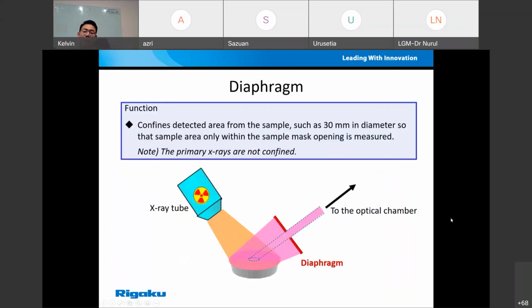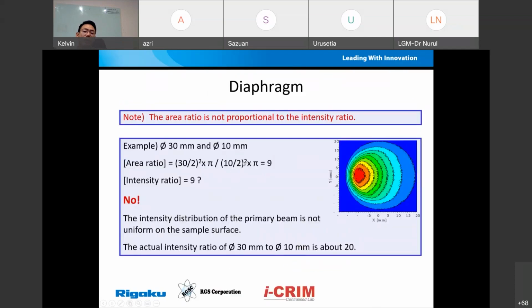Another part is the diaphragm. The diaphragm limits the X-ray beam size that can go into the detector. So if, let's say, you are using a 30 millimeter diameter sample ring, you will need to choose the 30 millimeter diaphragm. So it is related to which sample holder you are using. If I'm not mistaken, in UKM they have 10 millimeter, 30 millimeter, and also 40 millimeter. The different sizes depend on your sample size. If your sample is very small, you can use the 10 millimeter, or if your sample quantity is a lot, then you can use a 40 millimeter. In the software itself, you can choose the different diaphragm.